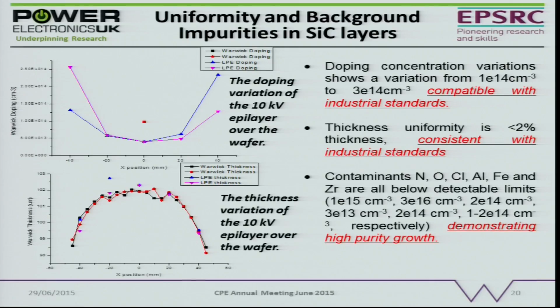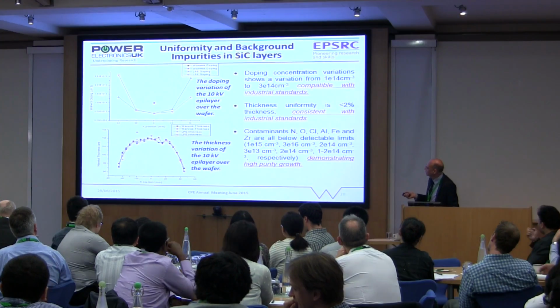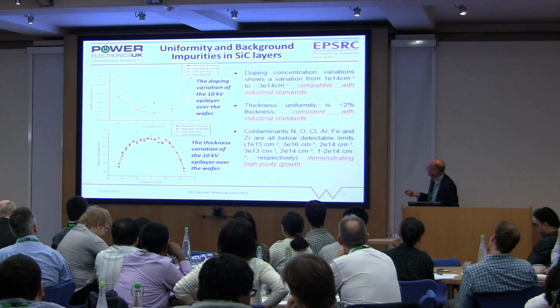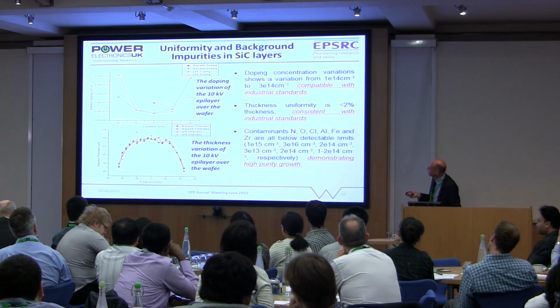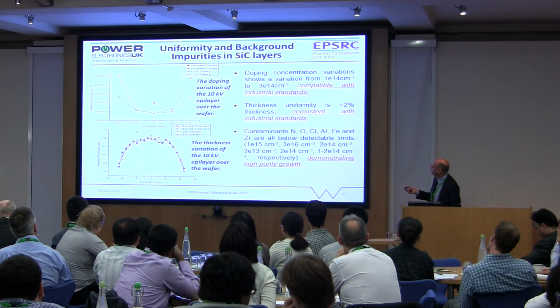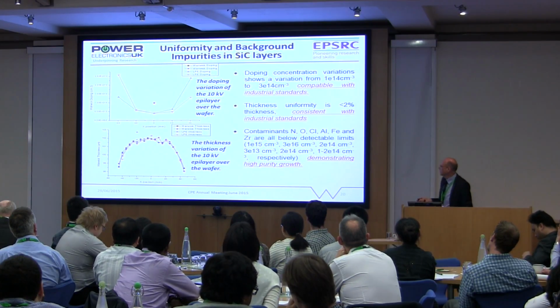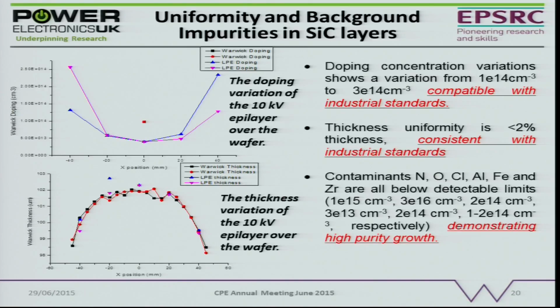We've also done some mercury probe measurements on those wafers to look at the variation of the thickness across the wafer and the doping. And here you can see that we've compared again our wafers with a company we bought the material from, and it's pretty good. There's our one in the middle there. The doping could be a bit lower, but it's quite acceptable for a first 1 or 2 runs.